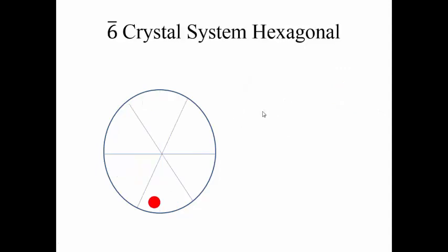And similarly for the 6 bar, we're going to go counterclockwise by 60 degrees, and we come out above the plane up there, and now we continue on and we find we get these 3 bullseyes. Of course we have 6 points that we're generating, so the order is going to be 6, and whenever you see this bullseye effect, you're going to know that there's a mirror plane in the plane of the computer or the plane of the board, whichever you're looking at.